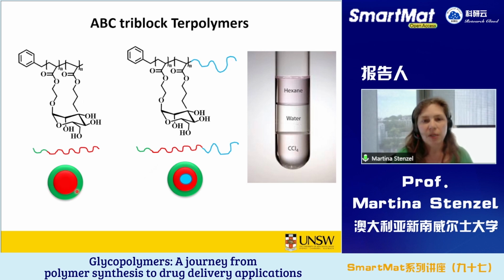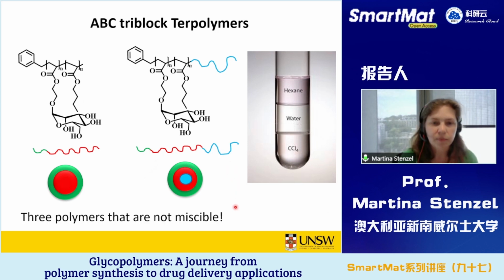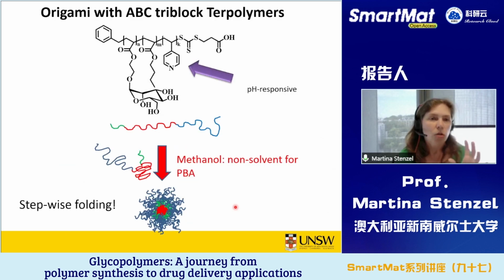However, when we work with polymers, we have a lot of freedom to operate, and we can work, for example, with tri-block copolymers. And these three blocks are immiscible with each other, similar to hexane, water, and carbon tetrachloride. We can work with three blocks that are not miscible and fold them in a certain way. What we've done here is, again, we use the glycopolymer, a hydrophobic polymer, and then a block that helps us with folding. This is a very interesting polymer because it becomes very water soluble in acidic conditions, but it's not water soluble in alkaline conditions.